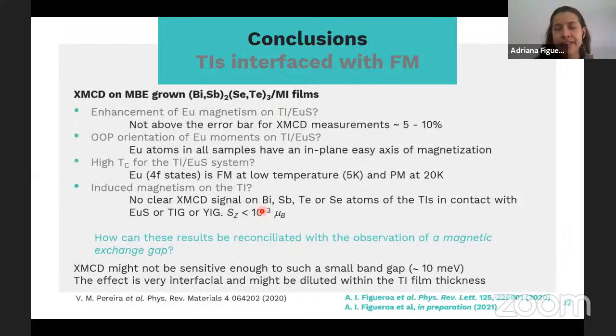And then the second part was about the other materials that we used as interfaces with the TI: magnetic insulators, europium sulfide and iron garnets. And the take-home message in this case is that there was no clear signal on the TI atoms in contact with these magnetic insulators.